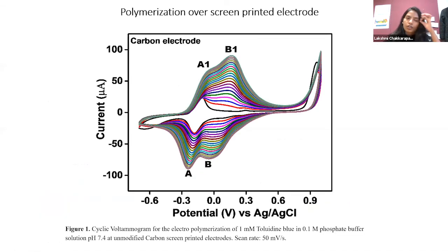And then here you could see the cyclic voltammetric response of the polymerization of polytoluidine blue. So we put 1 millimolar toluidine blue in phosphate buffer solution, pH 7.4. So we use an unmodified carbon screen printed electrode. You could see 2 redox peaks appeared. One appeared at -0.3 volt, A and A1, and the other redox couple appeared at 0.0 volt, B and B1.